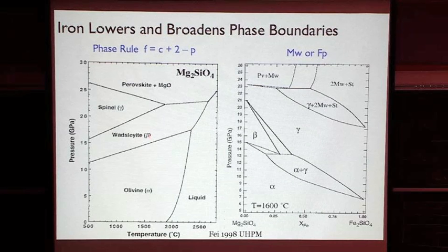And then as a result, at a given condition, for instance, over here in this region, maybe this phase boundary, you see that you have a phase loop over here. If you are at this pressure and with a certain amount of iron, you could have two phases coexisting. And that coexisting phase and the partitioning of the iron between the two phases, let's say we look at this transition over here from alpha to beta, at 14 GPa, you have a transition here, then you would have an alpha phase that is relatively poor in iron, and a beta phase that's relatively rich